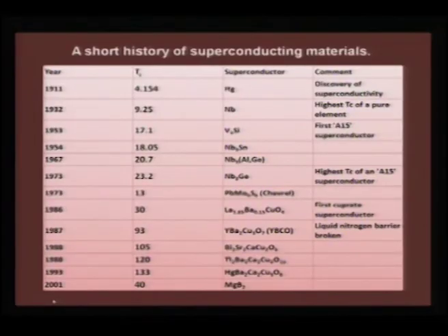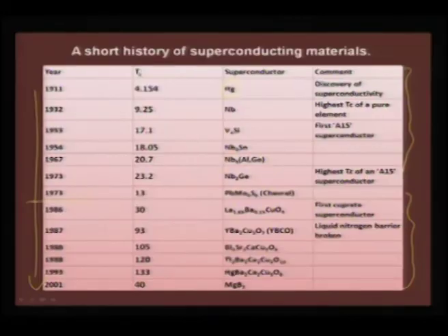Now, if you look at this short history of superconducting materials, you would see, from the finding of superconductivity in mercury way back in 1911, as you scan through, there is a shift in focus after 1973. Since then it has been mostly on oxide chemistry, whereas in the previous decades it was mostly on Chevrel phases or intermetallic compounds. So, there is a paradigm shift after 1986 where you start looking at the oxide chemistry in greater detail, and as you would see here, in most of the compounds that are listed, we have transcended from 30 Kelvin all the way up to 133 Kelvin. So, the quest is to go as close to room temperature as possible, so that the implications of superconductivity can be realized in the energy sector and in many other electronic environments.